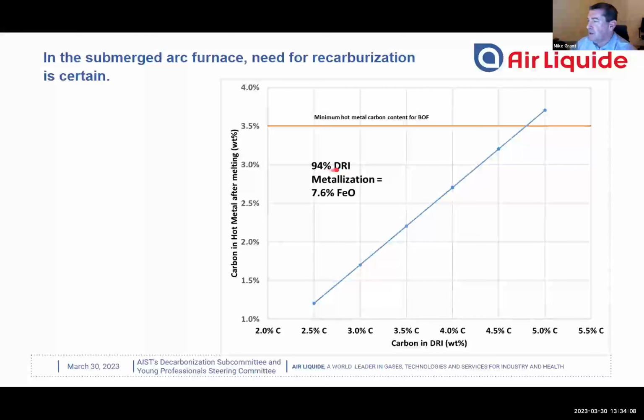And typical merchant DRI is about 94% metallization, which means 94% of the iron content in the DRI is metallized. This means about 7.6 or 8% FeO is in the DRI. And so when we produce a high carbon DRI and we melt that high carbon DRI, this FeO is going to attack the carbon first and use up quite a bit of the carbon. And so if we manage to produce a 5% carbon DRI pellet and we melt that pellet, we're only going to produce somewhere around 3.5 to 3.7% carbon in the hot metal, which doesn't give us a lot of room for use in the BOF.